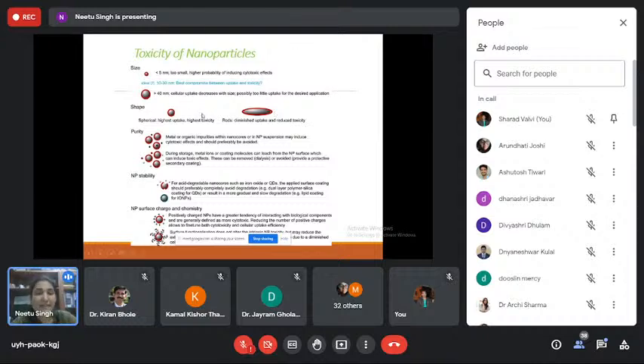So again, it's not very clear, but what I'm trying to tell you here is that the shape of the material can also cause toxicity, even though the composition is exactly the same. Talking about composition, metal particles are quite commonly used in drug delivery. Now, if the metal has some impurity or is doped with something, it can degrade and cause a lot of toxic effects. For example, inorganic quantum dots made up of cadmium and tellurium and things like that are very toxic, okay? Not because the nanoparticle is toxic, but because the elements used there are quite toxic to the cells. So how pure your material is also important. Otherwise, you'll get a lot of leachant.